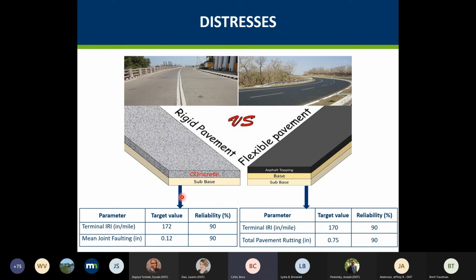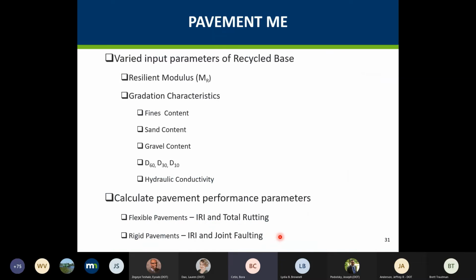And here are the distresses again for the rigid pavement ME analysis. We mainly focus on the IRI and joint faulting, and for the asphalt layer, since we're focusing on the base, we really focused on the terminal IRI, again International Roughness Index, and total pavement rutting values, and these are the target values and reliability values that we picked. So we varied the input parameters. These are the varied input parameters for the recycled base aggregates that we used, and we varied the resilient modulus, and the following gradation characteristics and hydraulic conductivity value, and then we calculate the pavement performance, again both for flexible and rigid pavements.